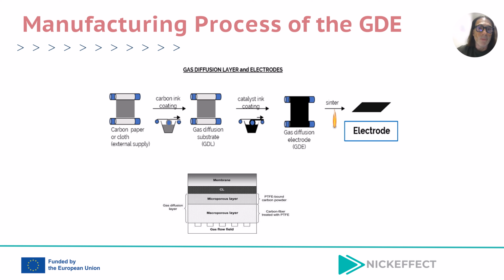Let's now walk through the manufacturing process of the gas diffusion electrode, or GDE, an essential part of the membrane electrode assembly. The process begins with the preparation of a conductive support. This is typically a carbon cloth, carbon paper, or metal mesh. We refer to this as the web and it forms the foundation of the electrode. Next, we apply hydrophobic wet-proofing layers to the web. These layers are critical. They help manage the delicate balance between gas and liquid inside the electrode, ensuring that gases can diffuse properly while preventing flooding.